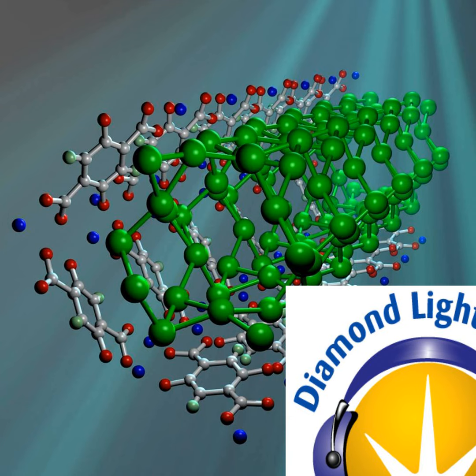Well, learning the crystal structure for these MOF materials is very important to understand their excellent properties and functions. MOF materials often crystallize in very small size, a few tens of microns typically, and if lucky, you may get crystals in 100 microns. The structural determination for crystals in such small sizes is very challenging. As I mentioned earlier, the high level of the porosity of MOFs, which is the most important feature of this type of material, will add more difficulties to this structural determination process.